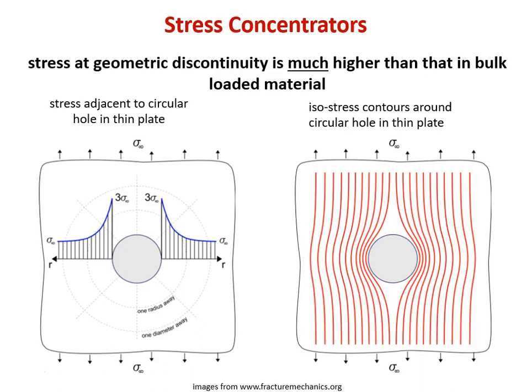Apologies for the interruption. Okay, stepping back from the crack tip and thinking a little bit more macroscopically. If we have a real part, it's probably not a uniaxial cylindrical test bar. It probably has some geometry to it. And anytime we introduce some complex geometry into a part, we have the potential for introducing stress concentrators. And these are very, very important for understanding what the real stress state is in a material. We will take this to a more extreme conclusion and actually look at the stress state at the tip of an atomistically sharp, very small crack. But we can use that same concept of stress concentrators to look at macroscopic design features like holes and thread roots and fillets and section thicknesses that aren't flaws but are actually design features in a material.